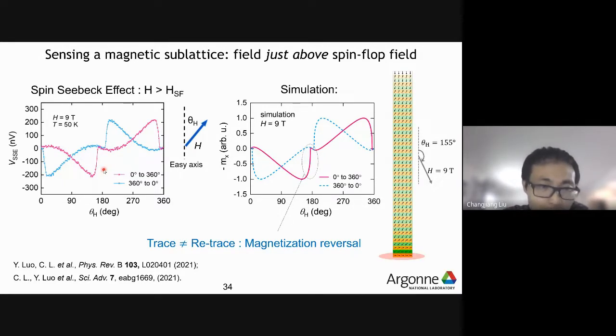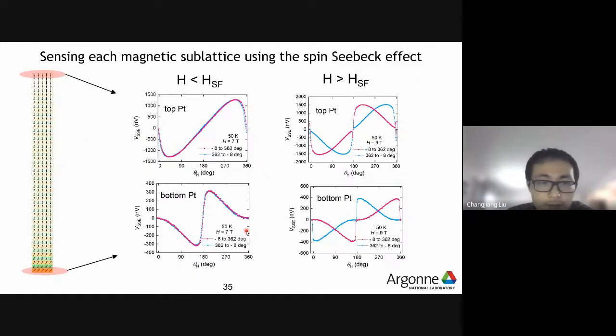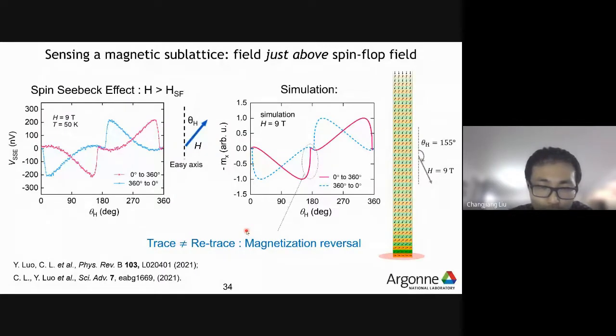and if that magnetization also experiences an anisotropy, you will typically see a hysteretic behavior. From the simulation, we found that this sudden jump is actually due to a spin-flop transition in this chromium-2-3. Once the field is above the spin-flop transition field, which is about 6 to 7 Tesla, you see this transition. And this behavior can also be nicely captured in our simulation, as shown in this figure on the right.